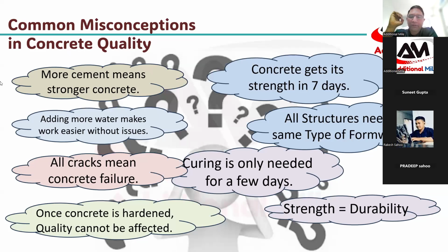Same way, another misconception is that concrete gets its strength in 7 days. As per practical results, concrete reaches about 60 to 70% of its potential strength in 7 days, not 100%. Standard reference strength is taken as 28 days, because hydration continues over time and strength can keep improving for months under good curing. When I say months, don't come to the conclusion that it is infinite. Again, the months will be limited by climatic conditions, limited to 56 to 90 days. It will never be unlimited.